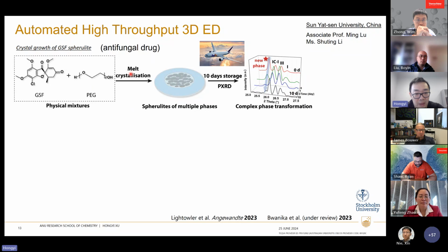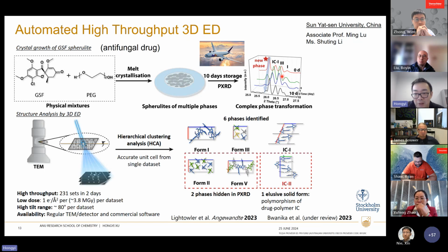So what they did was they grew this crystal with a melt crystallization method, and they thought this was a single phase. And the powder X-ray diffraction suggested it's a single phase. And then after 10 days of transportation with FedEx, so they're actually doing the synthesis for us, what we got was actually a phase mixture. So when we did the powder on this spherulite, the powder pattern actually changed from a single phase to multiple phases.